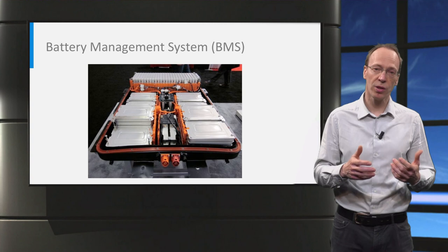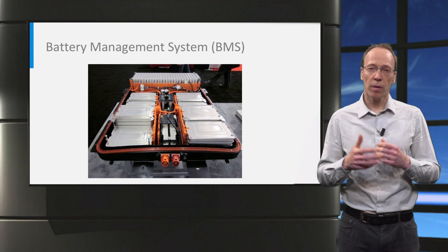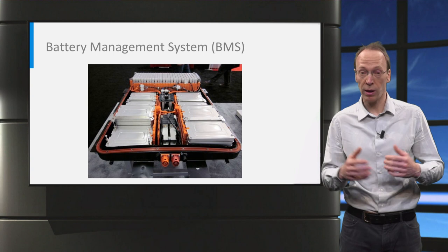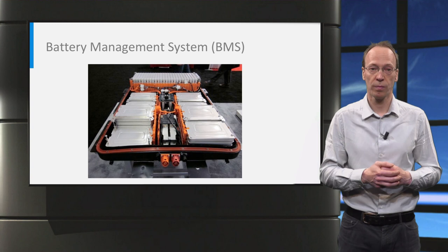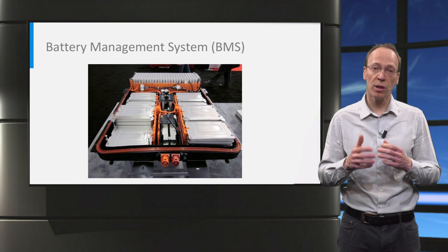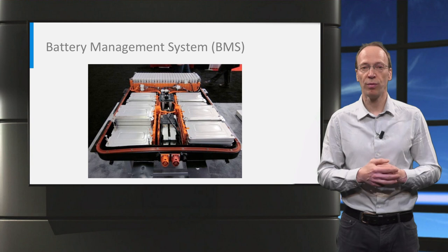One of the most important roles of the BMS is to balance the state of charge of the individual cells. This is to prevent individual cells from being at a relatively high or low state of charge, which would expose the electrolyte to relatively large overpotentials and, as discussed, may lead to electrolyte degradation — one of the major contributions that shortens cycle life. There are several ways to achieve balancing; a sophisticated approach is to shuffle the energy from the highly charged cells to the least charged cells. In this way the BMS is vital to achieve a long cycle life of the battery pack, in combination with providing optimal performance.